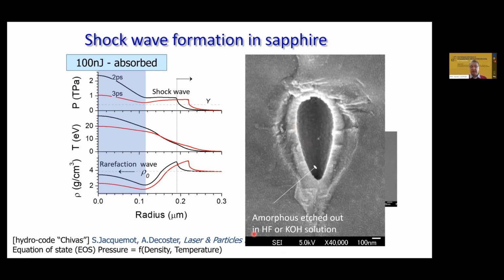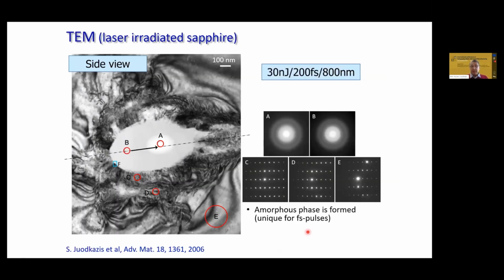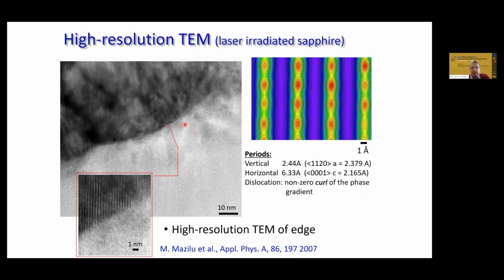An amorphous state can be washed out in acidic or basic solutions, and if you capture the amorphous state, you can see it in transmission electron microscopy. This is the volume modified by a single pulse, just at the threshold when the opening of the void happens. If slightly larger energies are used, this would be the void, and all this volume is amorphized, as seen by electron diffraction. X-ray diffraction I will show later. All these nearby regions are perfectly crystalline. The rim can be very sharp, so you have amorphous and crystalline phases happening on a nanometer scale.